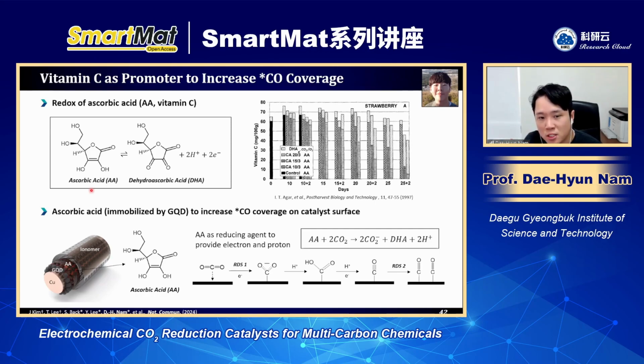Inspired by this phenomenon, we try to apply ascorbic acid to the surface of the copper. It means ascorbic acid can promote the formation of CO from CO2, because this is the RDS for CO formation. And if we promote the electron and proton transfer, this will help increase the coverage of CO, and this will be very effective to enhance the current density. So we try to put this ascorbic acid on the surface of the copper.